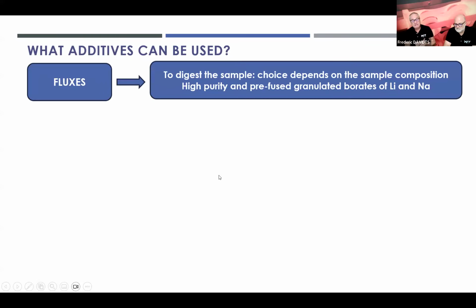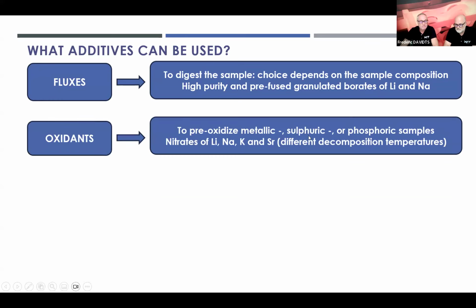There are a number of additives that can be used, that shall be used, and that have to be used for making our fused beads, depending a bit on the sample we are looking at. But what we will always use, whatever the sample is, are the so-called fluxes. These are meant to digest the sample, and the choice of the flux will depend strongly on the sample composition. The fluxes are in general high purity and pre-fused granulated borates of lithium and sodium.